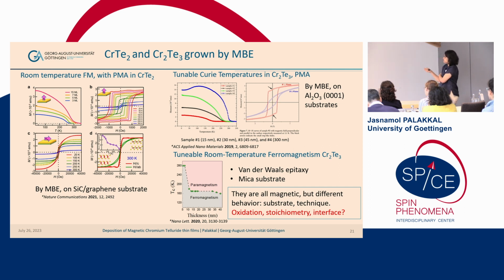And in these two cases, they were epitaxially stabilized by using molecular beam epitaxy, and most of the 2D people are working with van der Waals epitaxy. In that case, they take the big solid material and they use a scotch tape to get the layers out of the material. And when they tried it with van der Waals epitaxy, the trend in the TC is opposite to what they observed for the case of the epitaxial film. So overall, if you say that a material is magnetic, you should see if the magnetism is really originating from the lattice or if it is some extrinsic effect.